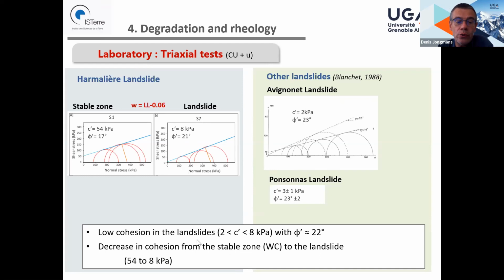So we show a low cohesion in the landslides with a friction angle around 22 degrees, and a decrease in cohesion from the stable zone to the landslides. I remind you that the 54 is for the weathered clay. Of course, in the sound laminated clays, the cohesion is much higher.